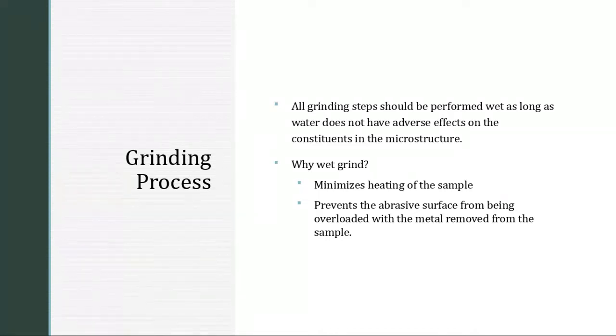So why would you wet grind instead of dry grind a sample? Well, if you dry grind a sample, you essentially heat up the sample—there's nothing to lubricate or cool. That's something we're trying to avoid, especially during long durations, since you're using these papers anywhere between 30 seconds to a minute long. If you left a sample on one of these abrasive pads for that amount of time, the sample ends up becoming way too hot to touch, and you can actually burn your fingers.